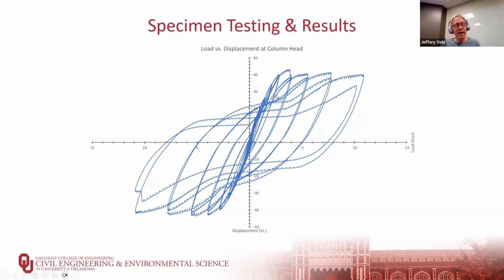That may be nonlinear behavior because, remember, again, we have a steel tube, a circular steel tube. So just like the reinforced concrete column, you're going to start to yield the material farthest from the neutral axis. So you're going to start to yield the steel tube at the tip. And then that plastic zone is going to grow as you plasticize the cross section. And of course, you're getting a nonlinear response because for part of the cross section of the steel tube, you're in the plateau region, which is inelastic and absorbing energy. But part of the steel tube closer to the neutral axis is still behaving linear elastically. So you have a combination of two.